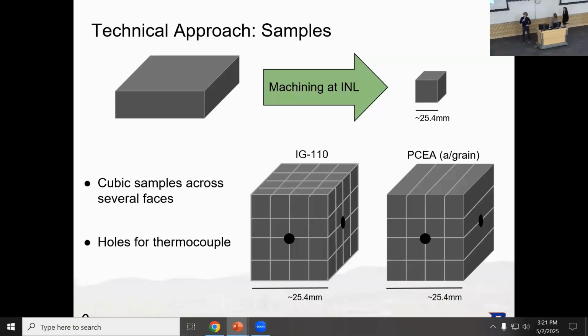On the bottom right, we can see the difference in isotropy within our samples. Our IG-110, the isostatic pressed sample, has this nice even structure on all faces, versus our PCEA, which has a preference with the grain direction, so we can see our against grain direction and our with grain direction. All of our samples did have holes drilled within them for the implantation of a type K thermocouple, which allowed the measurement of the true temperature of the sample. Our radiative measurements are taken on the opposite side of this thermocouple.